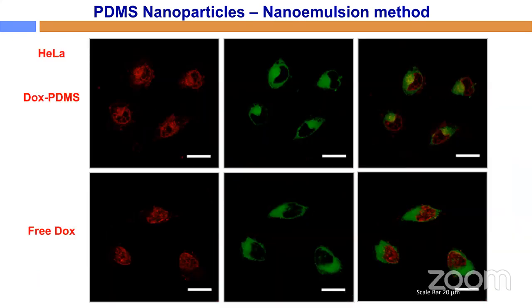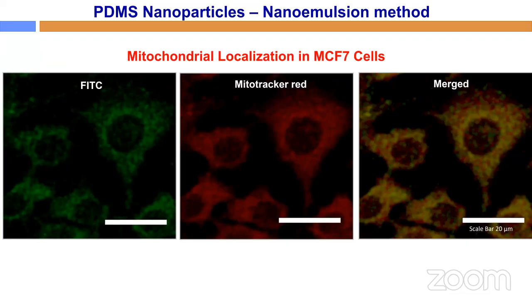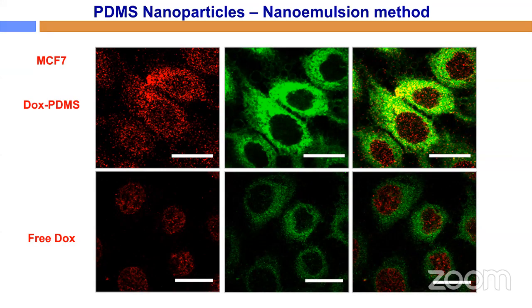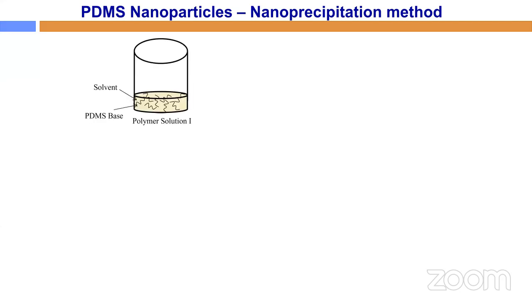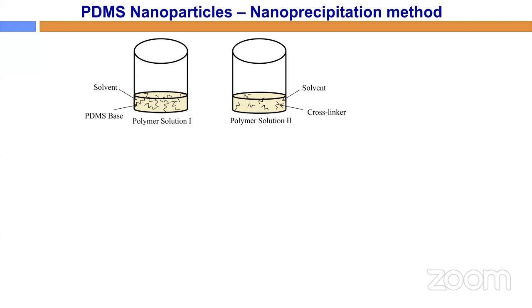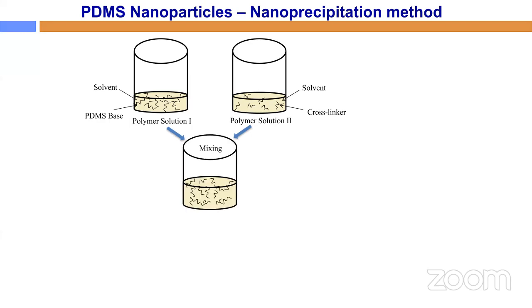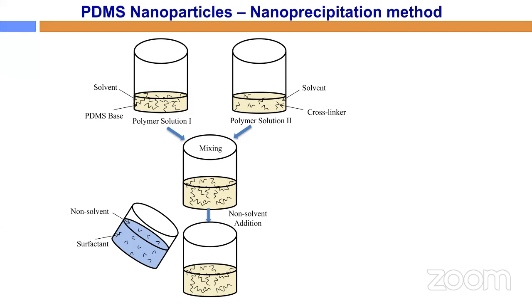So he has done different studies with the confocal microscope with different cells, but he is not very, very happy. So he has changed the method, to see whether the nanoparticle can target the nucleus or not. So he has done the nanoprecipitation method. In the nanoprecipitation method, he takes one base solution and another solution which is the cross-linker, mixes them together, and then adds the non-solvent with the surfactant.